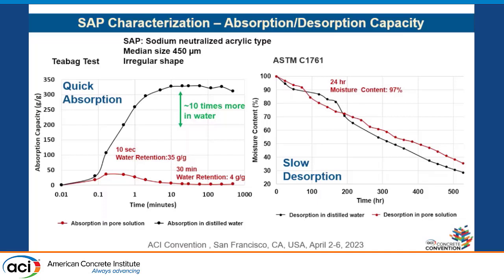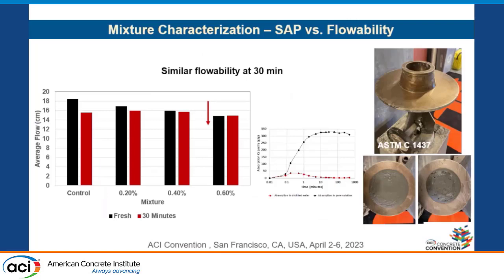And about the desorption, what you see on the right, it has a slow desorption, which is quite similar in water and also the pore solution. And just like I pulled up one of the numbers there, 24-hour moisture content is like 97%. It means that within 24 hours, SAP still holds its water. And technically, based on previous studies, after the first 48 hours, it starts releasing the water into the matrix, which provides enough water for the hydration of cement. But like I said, this affected our flowability.